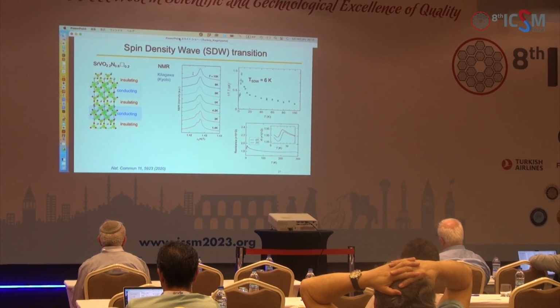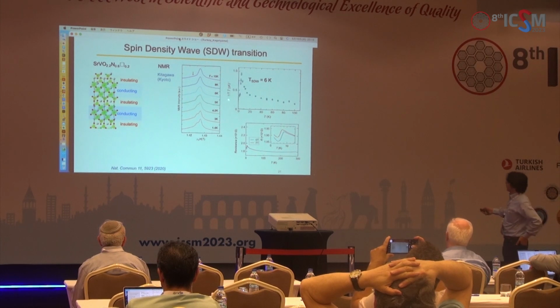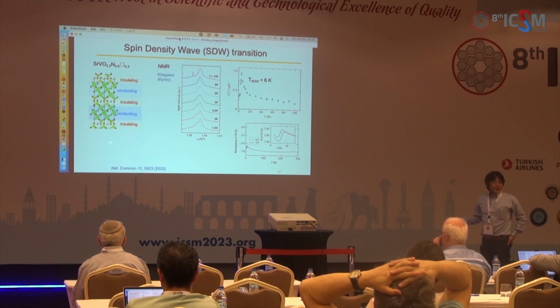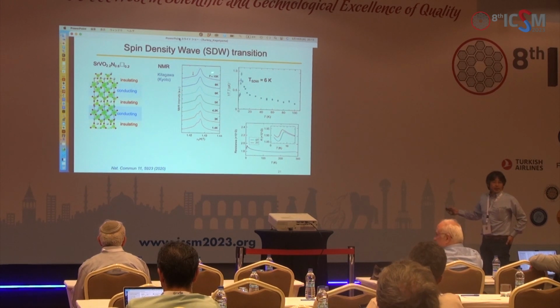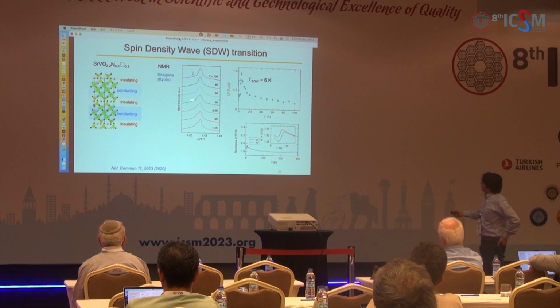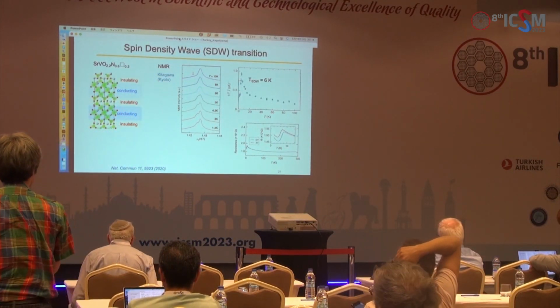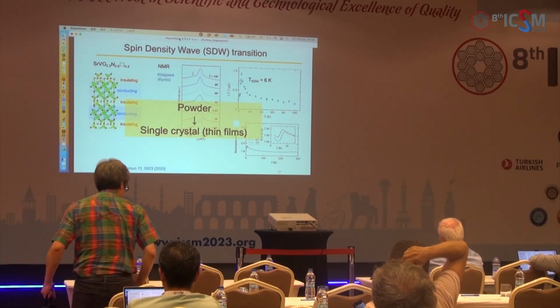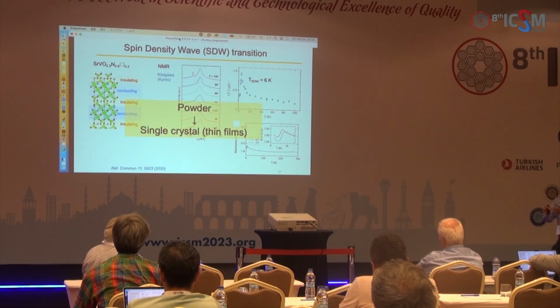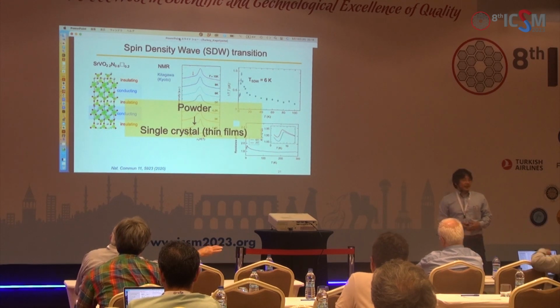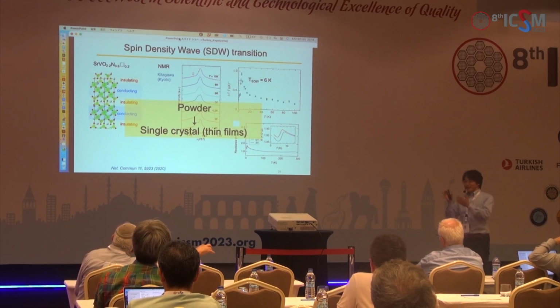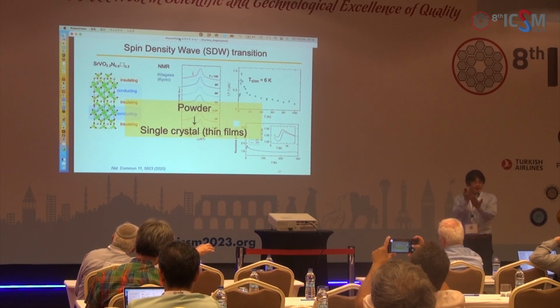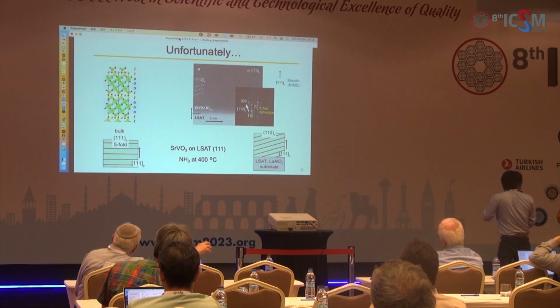Then my collaborator did several experiments down to low temperature, and we observed a transition at 6 Kelvin. It should be explained in terms of this spin-density-wave transition. This is a resistivity measurement. But the problem is that we started from a powder sample, so characterization of the properties is very difficult. The next thing we did was to try to obtain single-crystal epitaxial thin films.